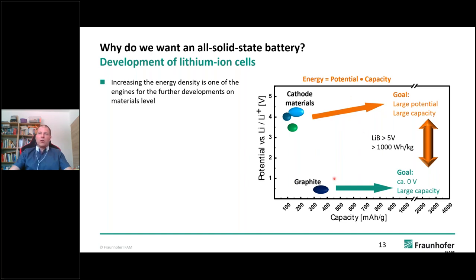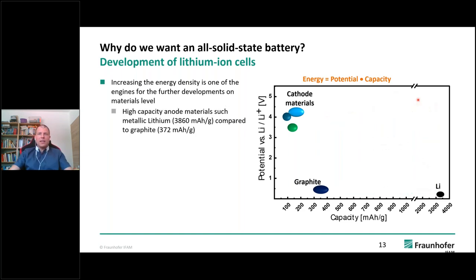So our goal would be to make an anode material which is around here, which is like 10 times higher, and make a cathode material which has maybe even higher potential versus lithium and also gives us a large capacity. Well, the development at the moment is that we can use different anode materials. Maybe one of the most important things is that we can exchange the anode material, the graphite, with metallic lithium, which would be the easiest way to handle this. This is like 10 times the capacity, which would increase the energy density by a very large amount.